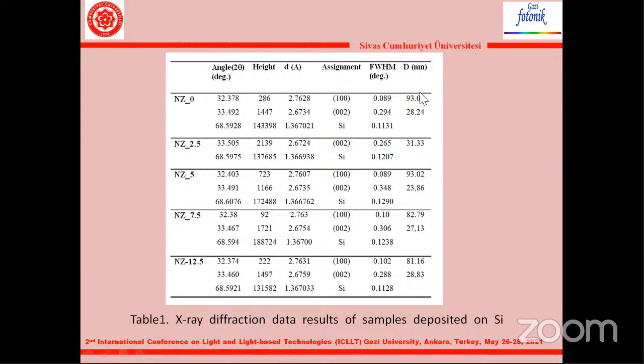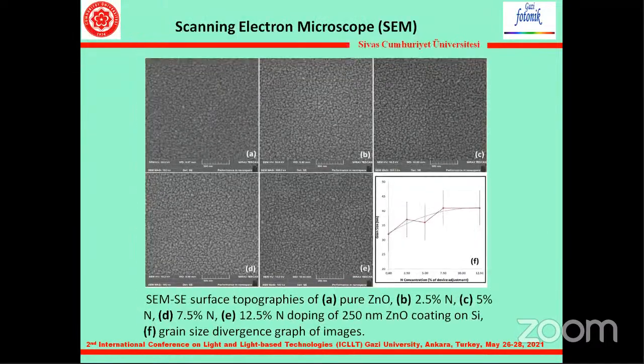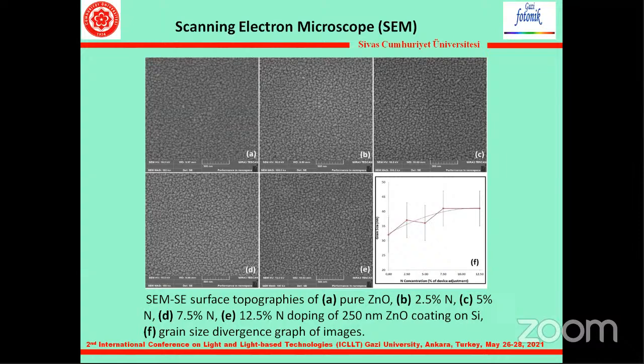As seen in Table 1, for the 002 orientation, grain size first increased, then decreased, then increased again. As a result, it behaves in harmony with the half maximum width and the particle size measured in the scanning electron microscope. Scanning electron microscope analysis was done on surfaces at 10 kilovolts with a working distance of 9 millimeters.